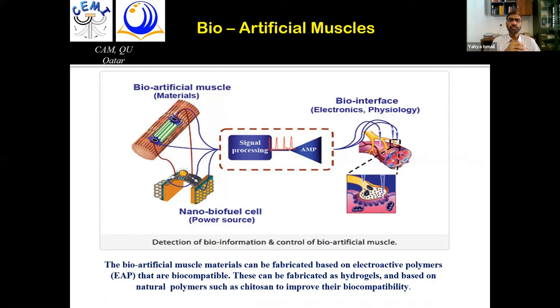So for a bioartificial muscle system, we may have to hybridize it with some kind of biopolymers. Biopolymers can improve the mechanical strength. Biopolymers can imbibe the water or the solvent molecules, and then transport the ions from the electrolyte to the polymer chain, the conducting polymer chain. So usually bioartificial muscle systems are designed by hybridizing with other polymers, usually hydrogels like PVA, chitosan, etc.